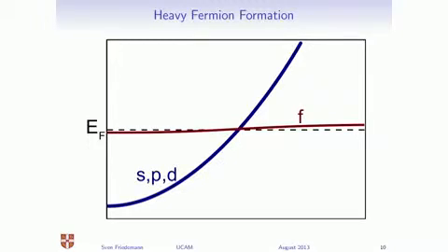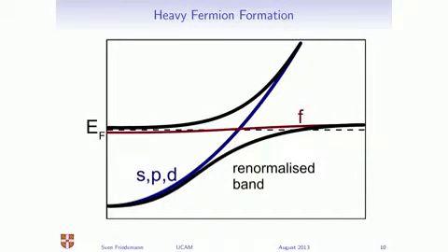The f electrons form one band very close to the Fermi energy, which hybridizes via the Kondo effect with the conduction electrons and thereby forms a renormalized band. This renormalized band has a much larger Fermi wave vector, constituting a large Fermi surface. LuRh2Si2 has a full 4f shell, lying well below the Fermi energy, and we are left with only the conduction electrons. In that sense, it represents a small Fermi surface reference to YbRh2Si2.